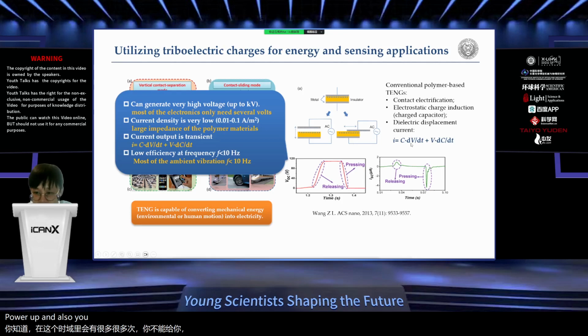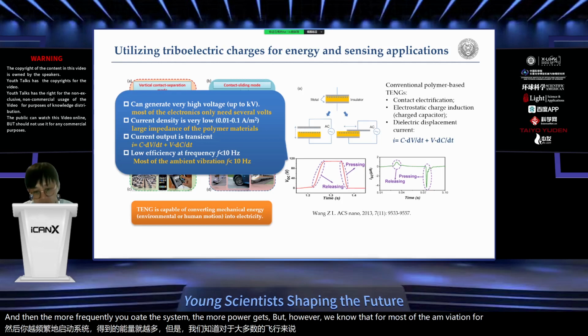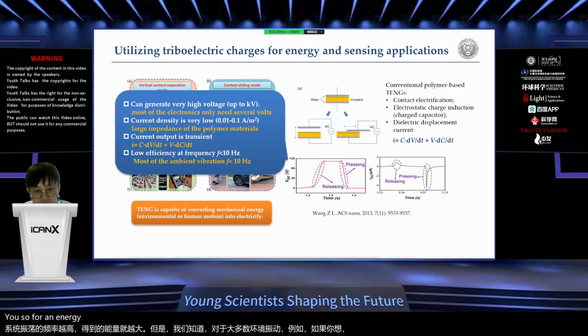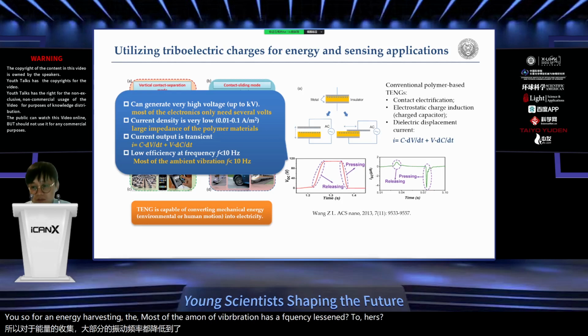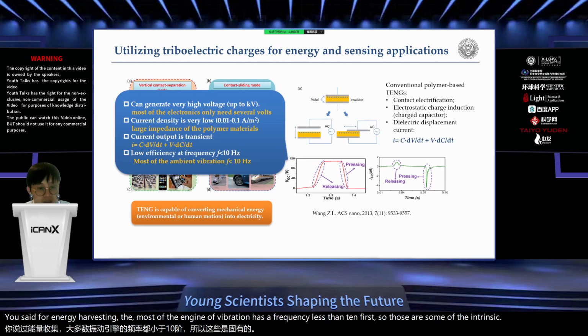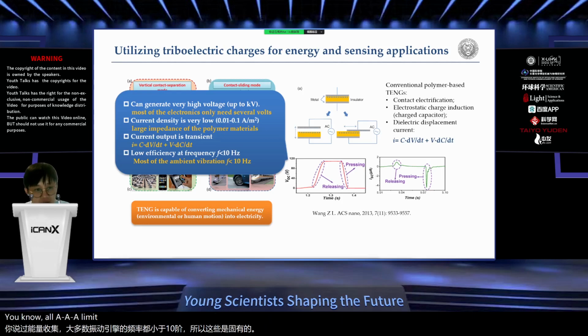And also you can see from this equation that the energy, the current outputs, depends on how fast you oscillate these systems, right? And then the more frequently you oscillate the system, the more power you can get. But however, we know that for most of the ambient vibration, for example, if you want to use that for energy harvesting, most of the ambient vibration has a frequency less than 10 hertz. So those are some of the intrinsic limitations of the traditional triboelectric generation.